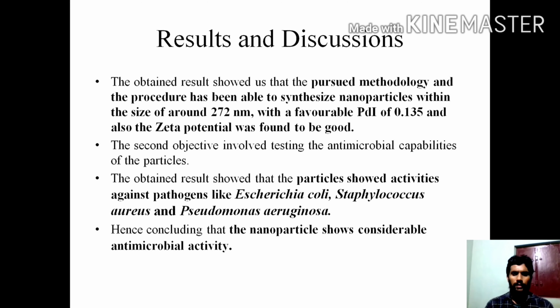The results that we have obtained showed us that the methodology that we pursued for the synthesis of nanoparticles has been able to synthesize nanoparticles of a size of around 272 nanometers, with a favorable PDI, that is a polydispersity index, of 0.135. A favorable polydispersity index has to be 0.5 or less than 0.5. So 0.135 is a good number, and also the zeta potential was found to be good.